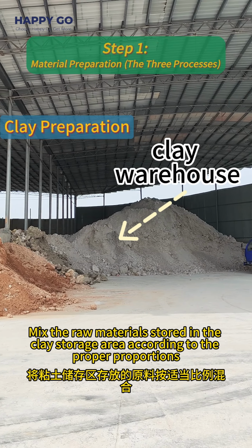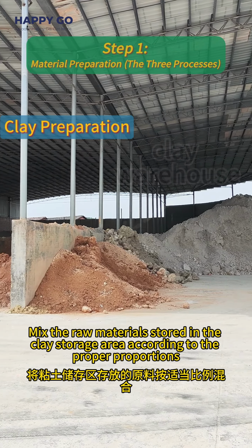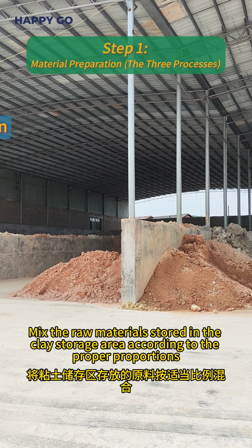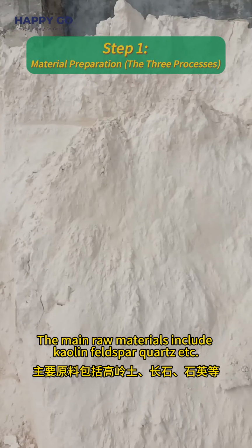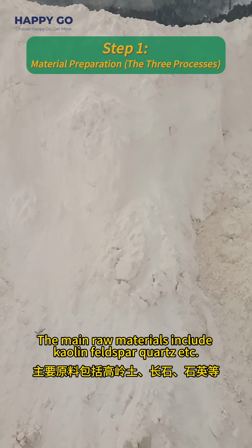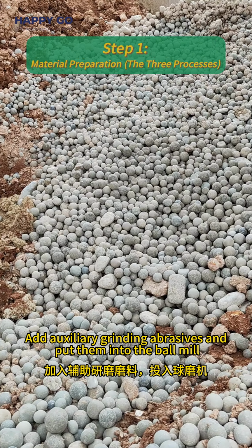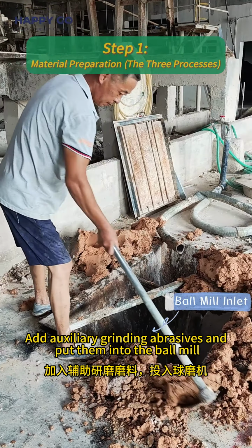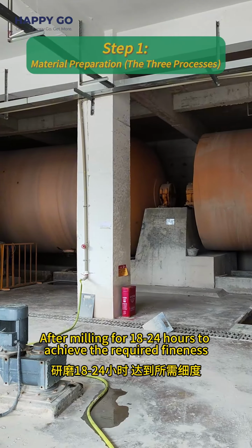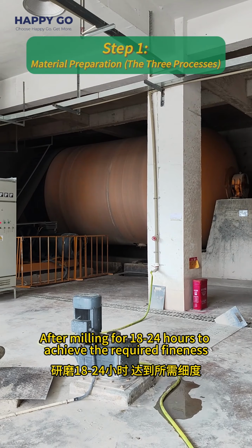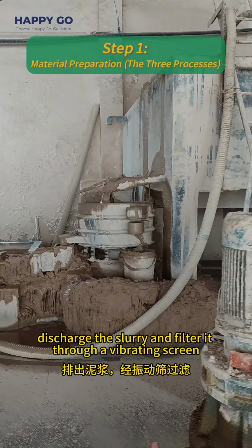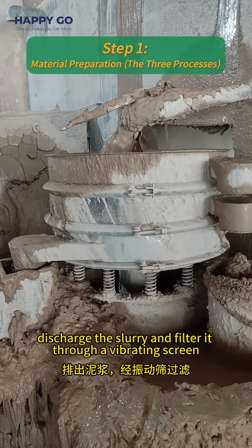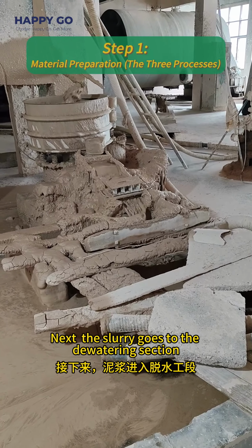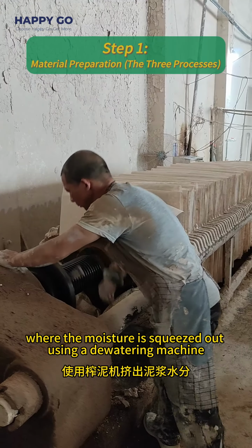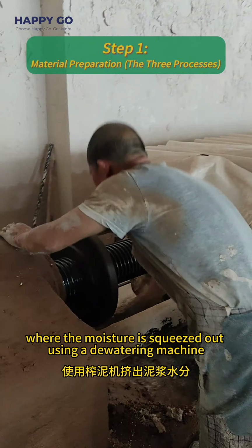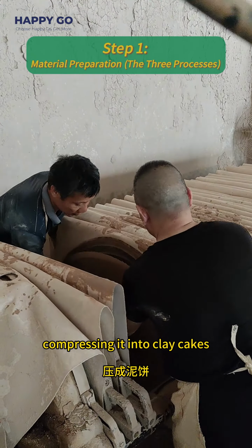Step 1. Mix the raw materials stored in the clay storage area according to the proper proportions. The main raw materials include kaolin, feldspar, quartz, etc. Add auxiliary grinding abrasives and put them into the ball mill. After milling for 18 to 24 hours to achieve the required fineness, discharge the slurry and filter it through a vibrating screen. Next, the slurry goes to the dewatering section, where the moisture is squeezed out using a dewatering machine, compressing it into clay cakes.